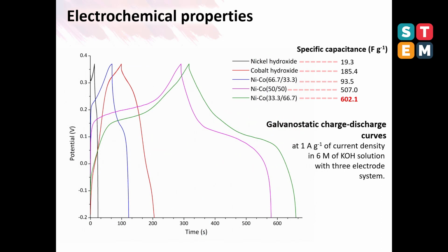The result corresponds with the GCD results. When calculating the specific capacitance from the discharging time of the GCD curve, the optimum ratio shows the highest specific capacitance at 602.1 farad per gram.